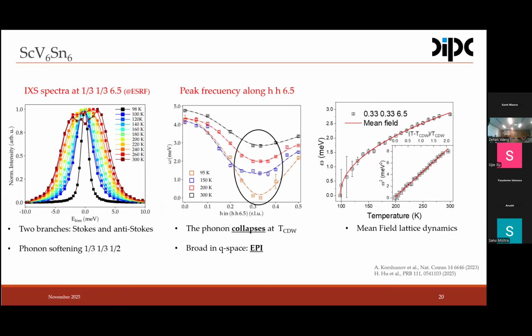I have a question. The Stokes and anti-Stokes branches mean the absorption and emission of the phonon. So if you cool down, I think one of the branches will not change, because one branch absorbs the energy, one branch emits the energy. One branch generates a phonon, another absorbs a phonon. Yeah, that's anharmonic behavior, and the phonon has to harden. Yeah, but now it softens because of the soft mode. That's the reason. I mean, if there is a soft mode, it has to soften, according to a phase transition, right? Okay. I mean, the normal behavior is that the phonon hardens.